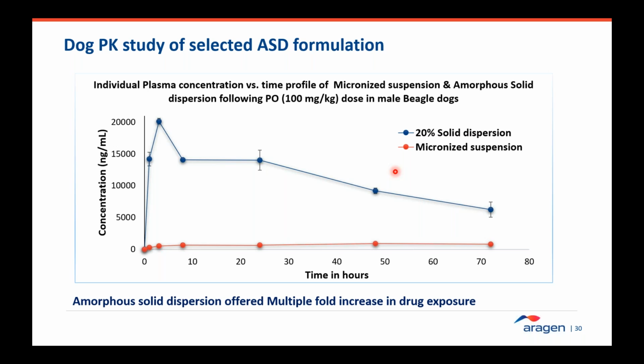And we conducted dog PK studies for these molecules, as well. As you can see, the micronized suspension, mainly because of precipitation effect, has very low bioavailability, and the solid dispersion showed very high Cmax, followed by sustained exposure because of the polymer, over a long period to almost 3 days. Which actually improves the AUC and exposure even more because of the sustaining effect of the polymers.